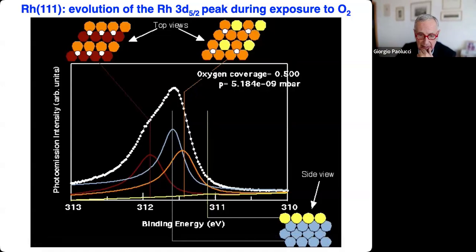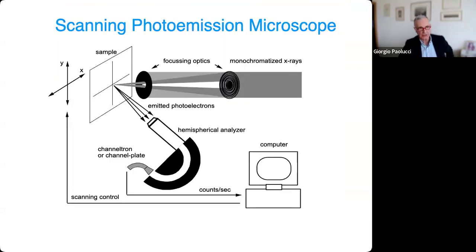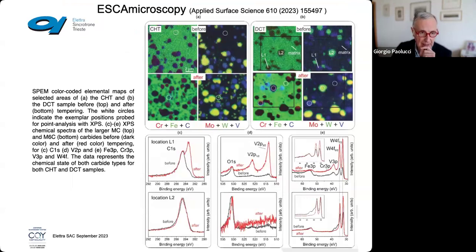For example, one thing that you can do with modern synchrotrons is focus your beam to a very, very small area of the surface. By moving the sample in front of the beam and of the analyzer, you can get nice maps of your sample. This is, for example, an alloy again with chromium, a chromium iron alloy in which you put a component. Then you can see the distribution of the various components on the surface.